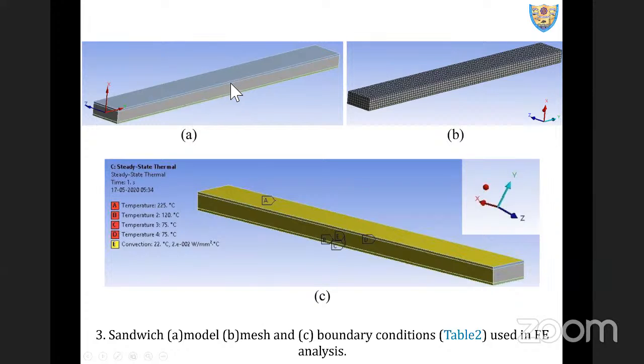Now what happens is, in this conventional manufacturing process, at the skin core interface, the adhesive, which is in the form of epoxy resin, is present, and thereby many of the sandwiches fail at the skin core interface. So if you have a methodology of producing the skin, core, and skin in one go and in one step, probably you are completely avoiding that common delamination failure at the interface of the skin and core, and completely enhancing the sandwich performance. And this we exploited in 3D printing. So what I'm going to talk about in the next few slides is how we did 3D printing of sandwiches.